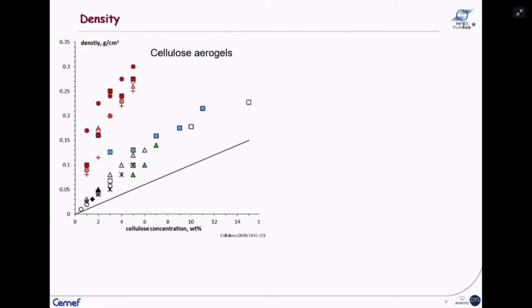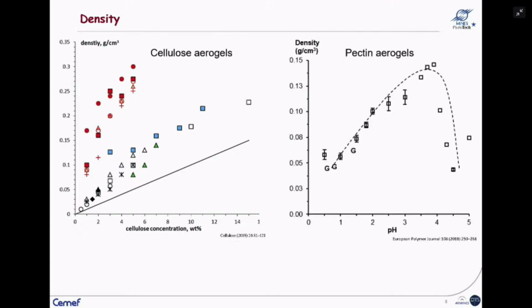We will not go into details on this. What is important is that there is this straight line which shows the case of no volume change during all the preparation steps. And all the data for density are above this straight line, which means that our sample undergoes volume contraction during all the processing steps, which is good, easy to predict, because when you are putting a polymer which was dissolved in a non-solvent, there will be a certain contraction, and then CO2 also is non-solvent for cellulose.